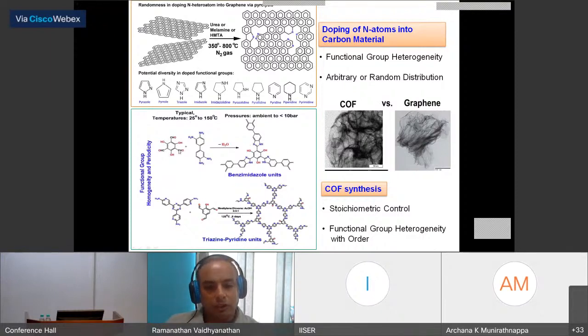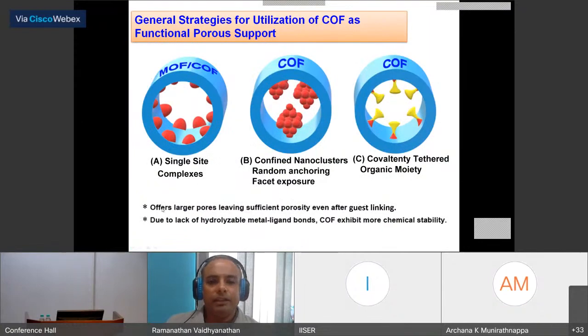Whereas if you consider COF, you are combining well-defined monomers in a stoichiometric ratio, and you are developing a very crystalline product where these functional groups are going to be periodically dispersed, and they are going to have very homogeneous site control. And this makes COF equivalent to graphene in some ways, but with more chemical control. And another interesting thing that you can do with a COF is that you can functionalize them with metal ions as complexes. That way you can develop single-site catalysts.